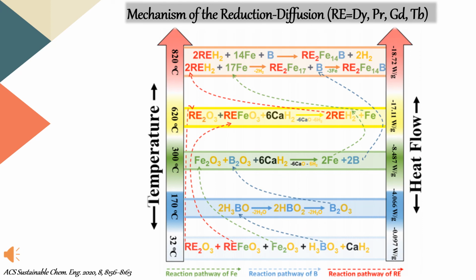This slide shows the mechanism of the reduction diffusion process. At 32 degrees Celsius there are all the reactants: the oxides, boric acid and calcium hydride. At the first step, at 170 degrees Celsius, the boric acid is changed to B2O3, and at 300 the oxides of boron and iron are reduced. At 620 some rare earth oxides are reduced, and ReFe oxides are also reduced. At 820 degrees Celsius the overall diffusion process is performed. The basis of this data is the TG data, available in the supporting information of our paper.